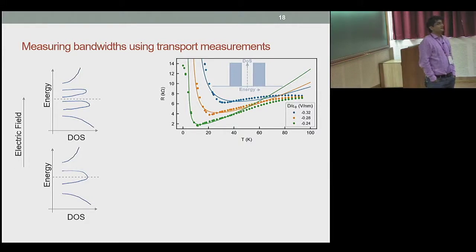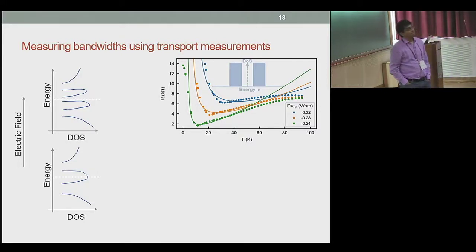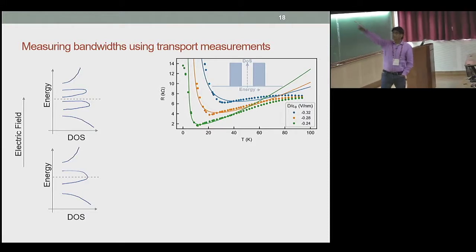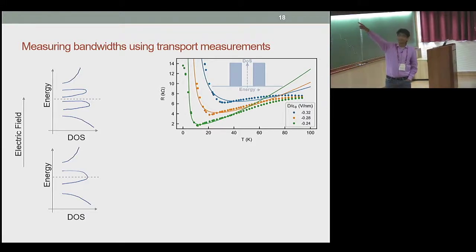So that's the only thing, the shape of the flat band density. All the resistance comes from activation. So the resistance is telling you the carrier density, or you have to assume different mobilities for the flat band. Yes, so we position ourselves for these extractions. We sit in the middle of the gap. There is a Moire gap on top of it. This metal insulator transition is because we sit at the charge neutrality point, precisely in the middle of the 2 flat bands.